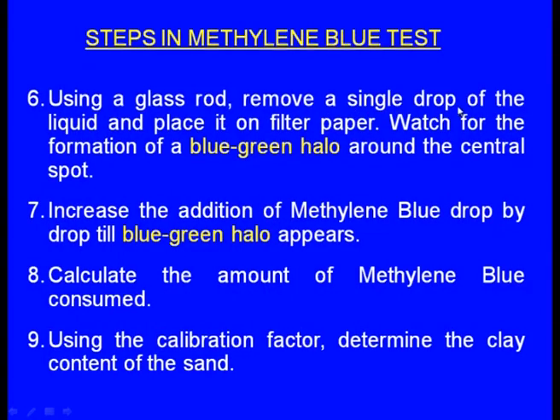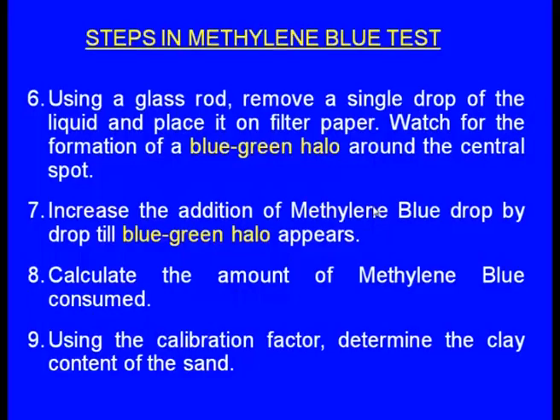Using a glass rod, remove a single drop of the liquid and place it on a filter paper. If the active clay is exhausted, there will be a little excess amount of methylene blue, and when you place that drop on the filter paper, there will be a blue-green halo around the central spot. This is the indication that the active clay is exhausted and methylene blue is dominating. If we do not see the blue-green halo, increase the addition of methylene blue, drop by drop, till the blue-green halo appears.